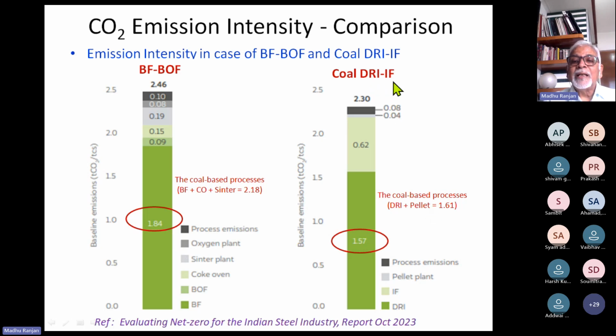For the DRI and induction furnace route, we can see DRI emission rate is 1.57, induction furnace 0.62, pellet plant 0.04, and process emissions 0.08. Here also, if we compare the emissions up to the iron stage, it adds up to 1.61, much less than what we find in blast furnace. But beyond this, nearly 0.7 tons of CO2 is generated by the steel making process, largely the induction furnace, which is run on electricity generated by coal.